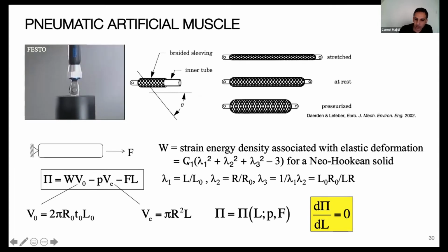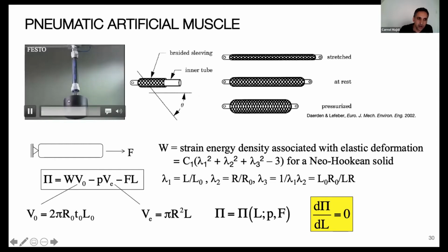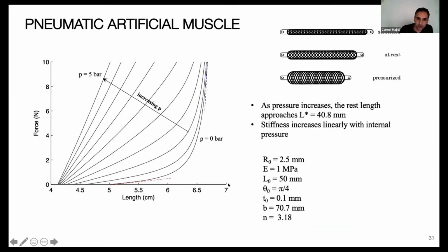Again, we see that C1 constant, we see the stretch components factor in. And then we also have the mechanical work terms, right? That was the other important component in our potential energy. And so here we have the mechanical work of that applied dead load, given by F times L. And then we also have the mechanical work associated with all that internal air pressure. And so when we minimize our potential energy with respect to the overall length of our actuator, we end up with solutions that turn out to be in very good agreement with what we observe experimentally with these types of McKibben actuators. Just in the interest of time, I'm going to speed through this.